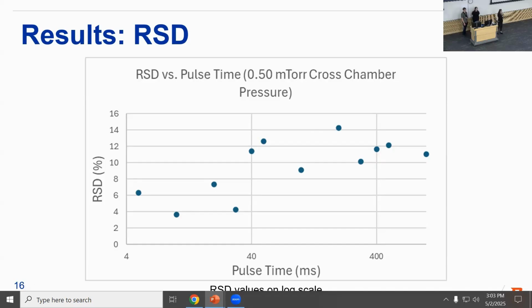Below 30 milliseconds, these RSD values are relatively low. Beyond 30 milliseconds, they increase significantly. They exceed about 10%. So again, these higher RSD values at longer pulse times indicate that precision diminishes as the pulse time duration extends. I would also like to mention that we did perform a Grubbs test to identify any outliers in our data. Throughout all the data sets, only the 30 millisecond data set identified a low outlier, and that data point was thrown out before we performed the statistics on it.